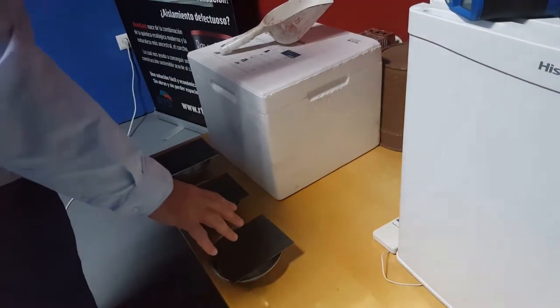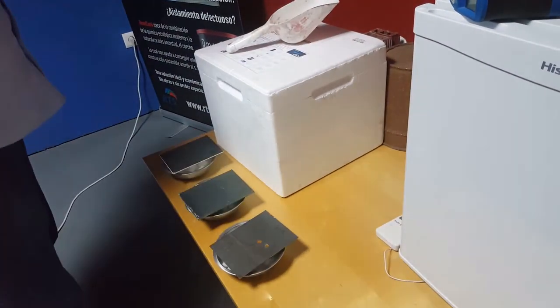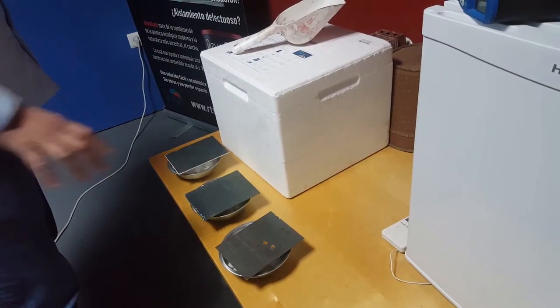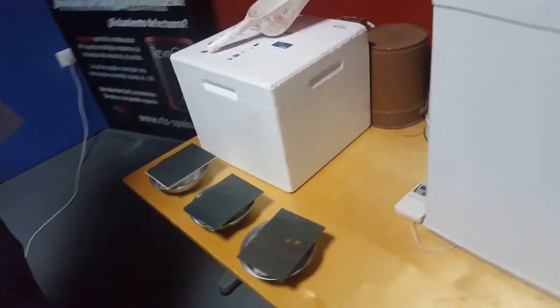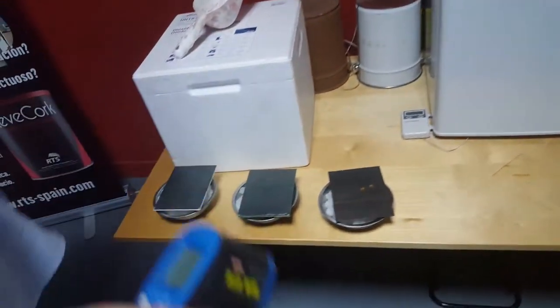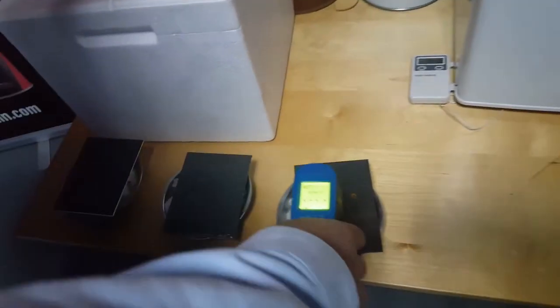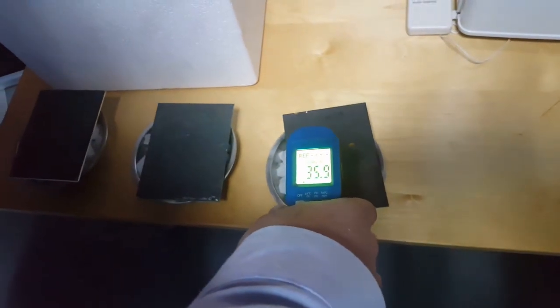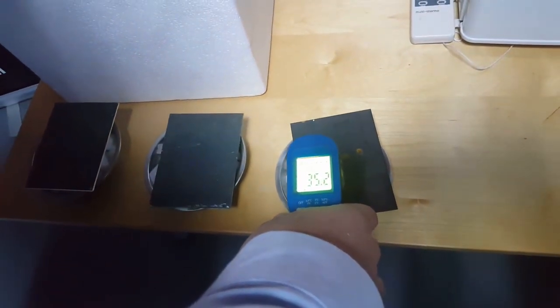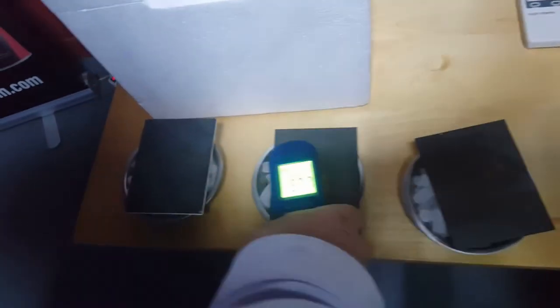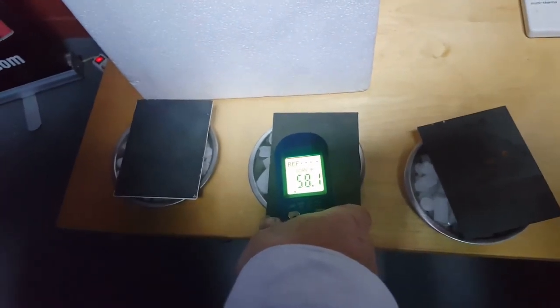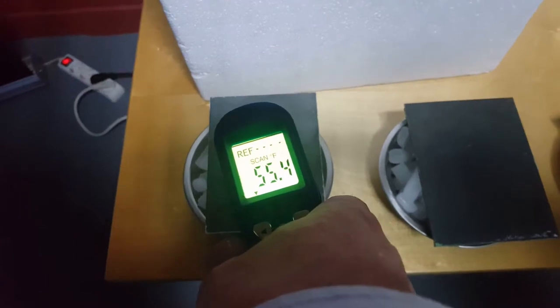So we'd expect the blank sample to cool down extremely fast. With the dry ice being so much colder than the room, there's really nothing stopping that piece of metal from cooling down. Our first measurement, less than a minute in, is around 35 degrees Fahrenheit and falling. The cork coating is around 58 degrees, and then the ceramic coating is around 55 degrees. So already we have about a 20-degree difference between the uncoated and coated samples.